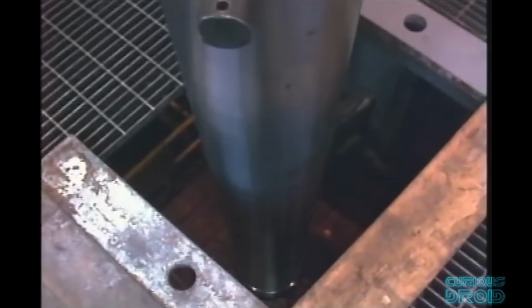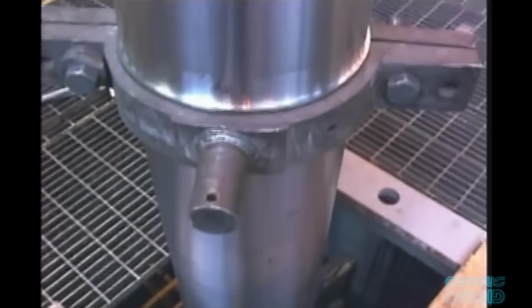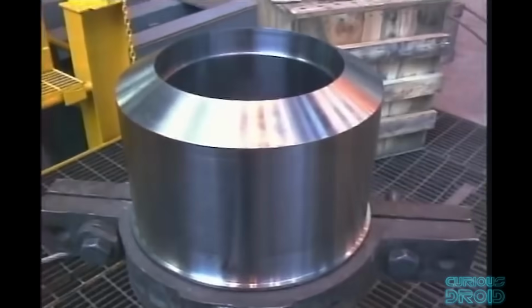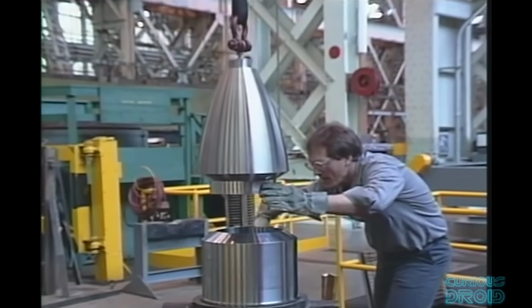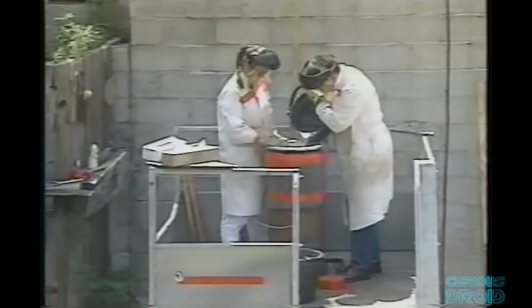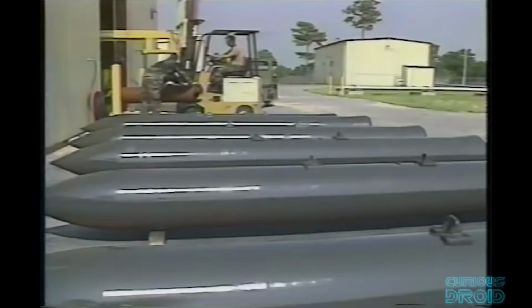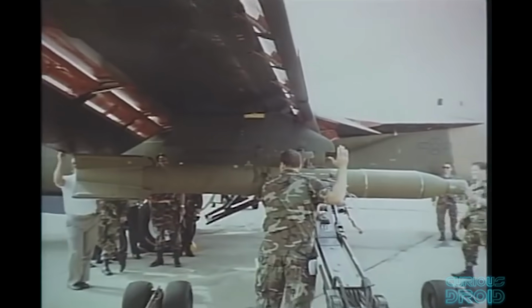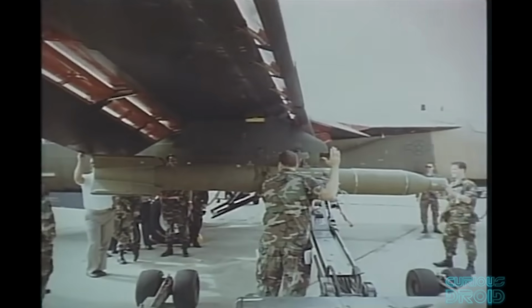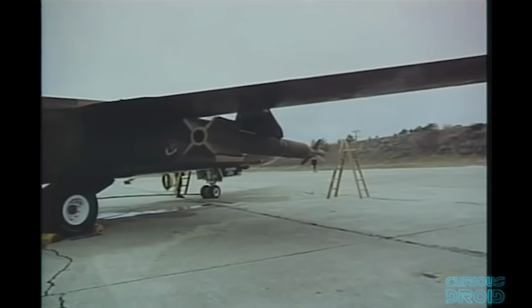At 19 feet or 5.7 meters long and weighing 5,000 pounds or 2,200 kilos, they were filled with 285 kilograms of explosive, fitted with a hardened nose cone, laser guidance and controlling fins from the GBU-27 LGB kits, and given the designation of GBU-28 or Guided Bomb Unit 28. In sled tests, it could penetrate 20 feet or 6 meters of concrete, and in flight tests, it reached a depth of 100 feet or 30 meters in earth.